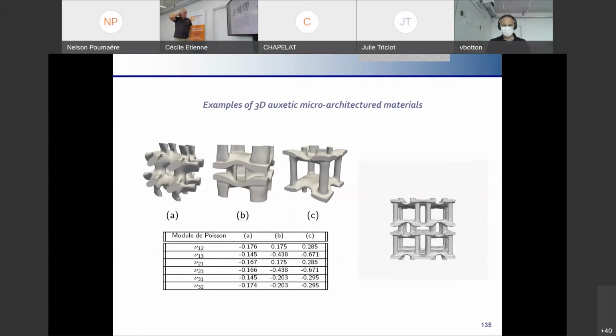As you know very well, standard materials in nature have only Poisson ratio between 0 and 0.5. It corresponds to incompressible materials for 0.5, but theoretically it was discovered more than 150 years ago that Poisson ratio can also be negative, until -1. However, in nature, it was not possible to discover a material with negative Poisson ratio. In other words, when you have a tensile test, you have an increasing of the profile uniform along the bar. Natural materials don't offer such a possibility, because in practice very often what we have is only a positive Poisson ratio. When you have a tensile test, you have a uniform decreasing of the profile.